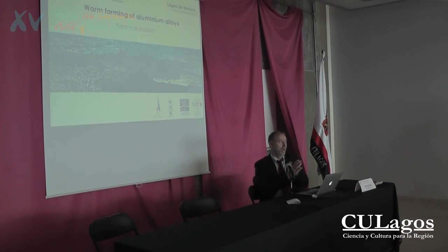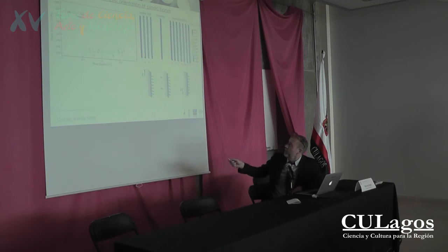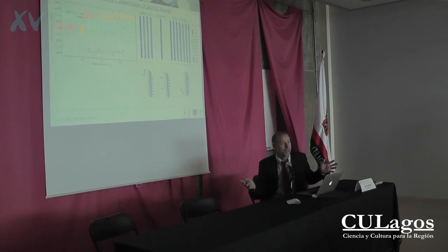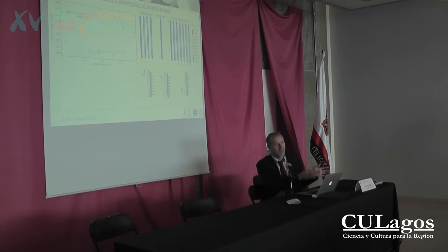I already did this kind of study several years ago. In fact, when you have an elastomeric material, you have, most of the time, only elastic deformation. This is different from what we have observed here. Because in a rubber, you will have a curve which goes like this, and when you unload the stress, you will mostly go back to the initial deformation. In this kind of metallic material, what you see is that when you reach here a high level of strain, when you're unloading, you're staying at the same point. So you can say that we have a very large hysteresis, but we don't have an unloading. You can only return in this region here. If we make a zoom here and we unload, we can return to the initial position. This is the classic distinction in metallic materials between elastic deformation and plastic deformation.